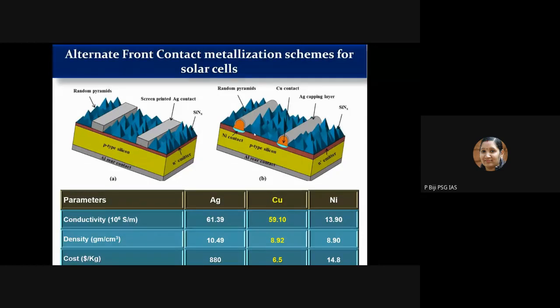Then in the second case, there is a difference in this metallization. It's a less silver process. I have a nickel contact over here as a seed layer, the main conductor is going to be the copper contact, and on top of that I have a silver capping layer. So this is one of the alternative metallization processes which can be considered.